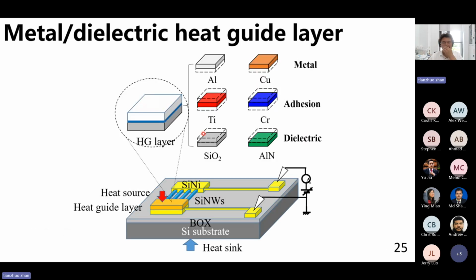And so next, we design the metal dielectric heat guide layer. So we know that metal thin film has a high thermal conductivity, but they are conductors. So we need to use a dielectric layer for electrical insulation. And so we use two kinds of metal. One is aluminum and the other is copper. And two kinds of dielectric material, silicon dioxide and also aluminum nitride. And we also use two kinds of adhesion layer. One is titanium and the other one is chromium.